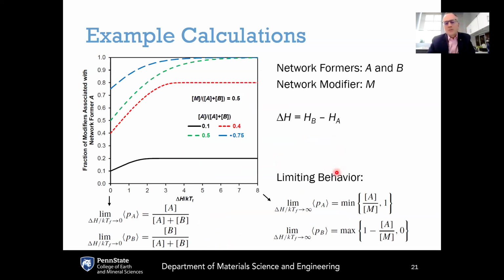This shows you some example calculations here. The y-axis shows the fraction of network modifiers associated with a given network former A as a function of delta H over kTF. So this would be the enthalpy difference between two different bond associations divided by kTF, the amount of thermal history at the fictive temperature where the supercooled liquid gets frozen into the glassy state. And if you have the limit of this delta H over kTF going to 0, so in that limit, that would mean that there's no effective energy difference between these two different states, or that the fictive temperature is infinite.